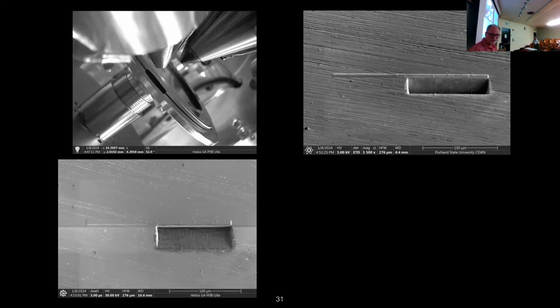This is actually the way this detector is configured. Instead of being an ion image, it's a secondary electron image using the ion beam as the generation source. So our sputtering is taking, as we're taking materials off, we're generating secondary electrons, which are defined in the physics world as having voltages of 50 electron volts and less.